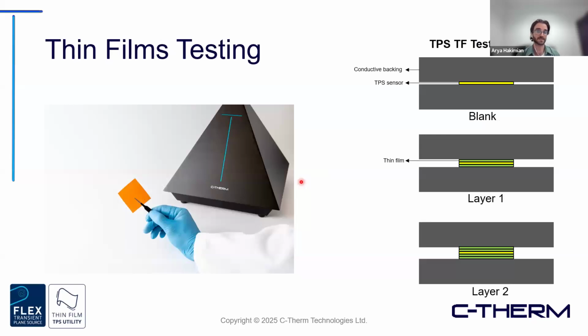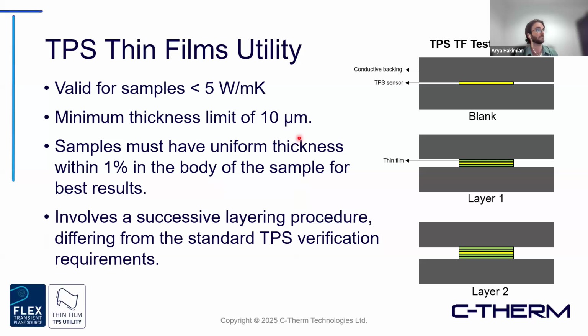The other thing, and this is the last example I have here for the thermal conductivity side, is thin film. So some of these packaging materials, there may be different barrier films or just plastic films involved in the overall system design. But thin film testing is a little bit different than your more traditional bulk material measurements. One of the big challenges with thin film is related to the thickness, right? However, on the TPS, we do have a utility to directly measure your thin film materials, looking at samples down as low as about 10 microns in thickness. So again, different methods, different benefits, and different geared towards different functions. But with the TPS, a nice way to measure your thin film samples.